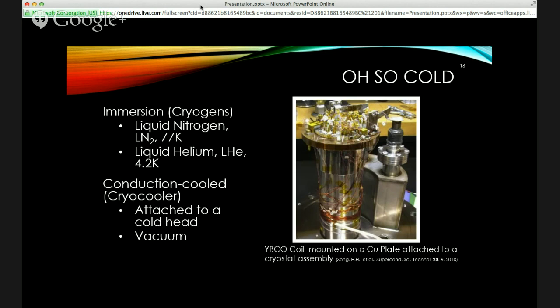So how do we cool these? I mentioned the cryogens before. Immersion is a way to cool them, meaning you would have a Dewar and fill it with liquid nitrogen or liquid helium. You put your sample in the Dewar and then conduct your test or operate whatever you're trying to do. Liquid nitrogen has a boiling temperature of 77 K, liquid helium at that 4.2 K range that I mentioned before. Or you can use a conduction cooling method, which uses what is called a cryocooler. Looking at the image, it's difficult to see, but all the connectors at the top, that is where your superconducting coil sits. It's a cold head, and it's vacuum pumped down, and then it uses the cold head to cool the superconductor.